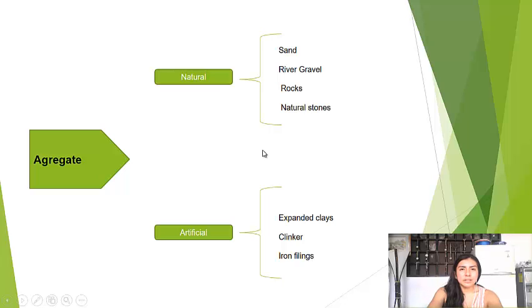Today, concrete that has recycled material is mostly used in non-structural applications because the quality of the aggregates influences the mechanical strength, and therefore there is expansion, cracking and low bond strength. It is for this reason that tests are carried out to determine this resistance, and from the results to promote a structural use concrete with recycled material.